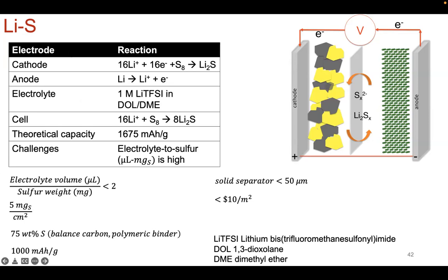Now you could see that at the anode side, we have lithium metal, and with all batteries thus far using lithium metal, you need lithium metal anode protection, right? This is not just for lithium sulfur, this is for all batteries that have a lithium metal anode. Protection is the key thus far. And so either you can have a physical material that protects, like solid electrolyte, or just your usual separator. But what has been seen in lithium sulfur is that just having a polypropylene separator does not do the job.